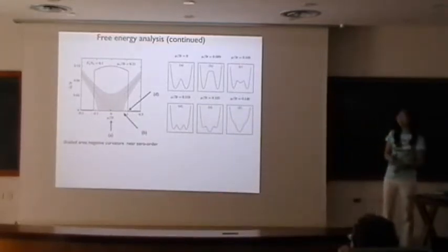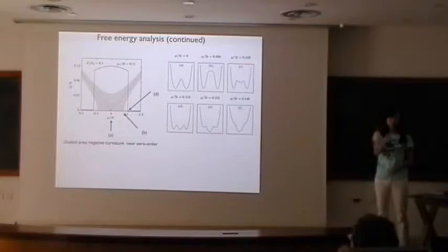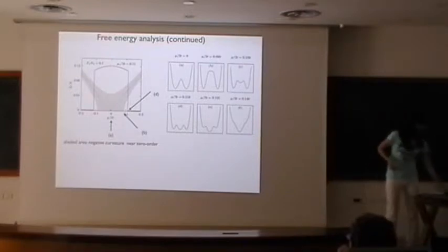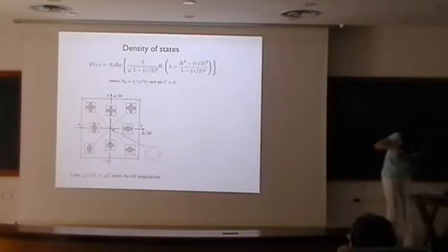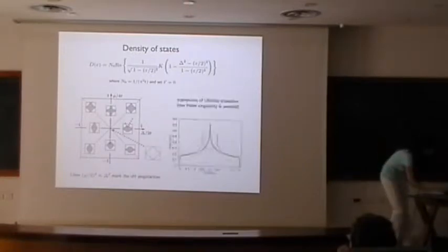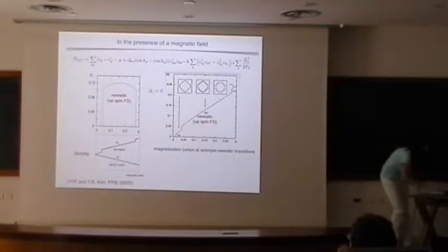And that doesn't depend on the details. You can put the t prime, t double prime, whatever, and wherever the non-interacting term has the Lifshitz point, that's where the nematic sets in. And the window and strength depend on the interaction. So that's why at higher magnetic field it goes back to the isotropic. So that's why there have to be two consecutive metamagnetic transitions, with nematic in the middle. Okay.